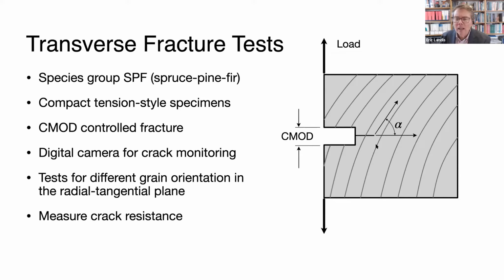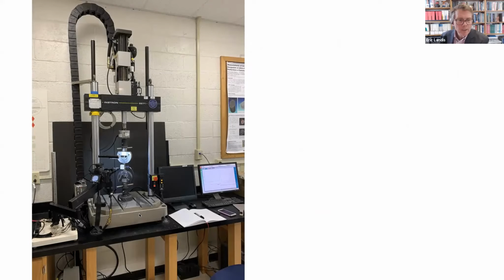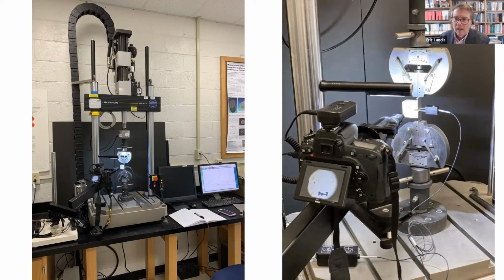And our interest here is to measure crack resistance, keeping in mind we have this variability between not only direction, but also the early wood, late wood differences in material properties. So we want to measure crack resistance with an eye on the material morphology. So our experimental setup, we have a closed loop load frame, showing the digital camera with a microscope lens attached, zooming in on the specimen.